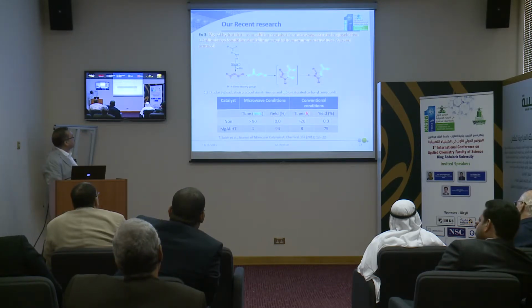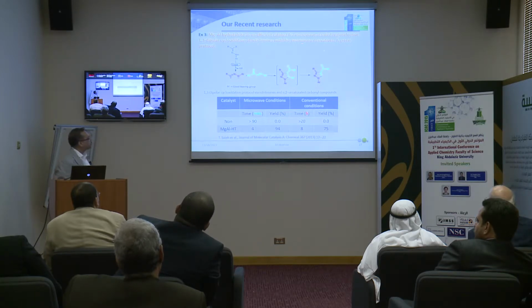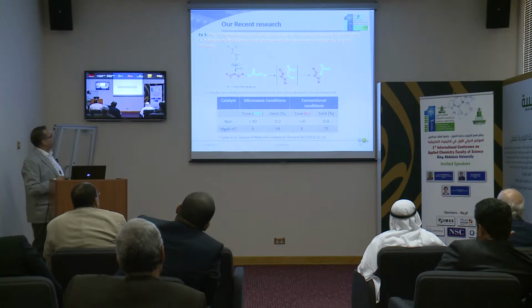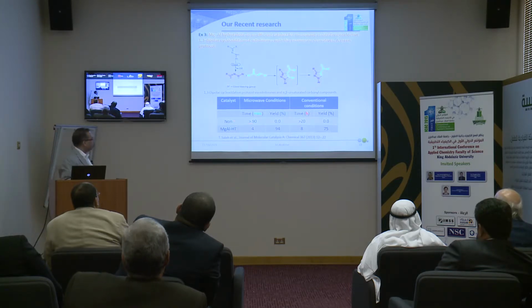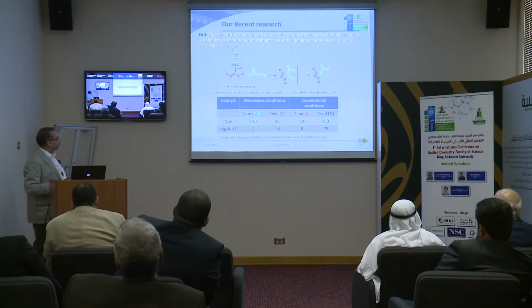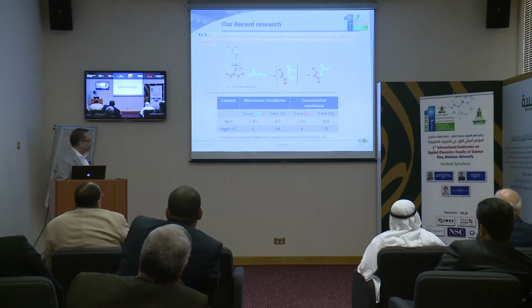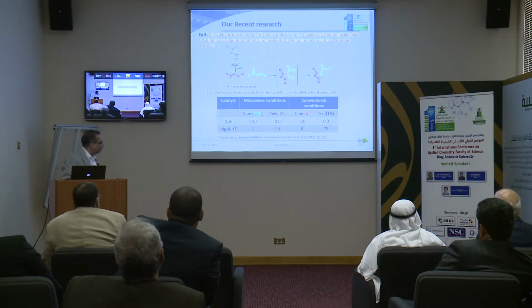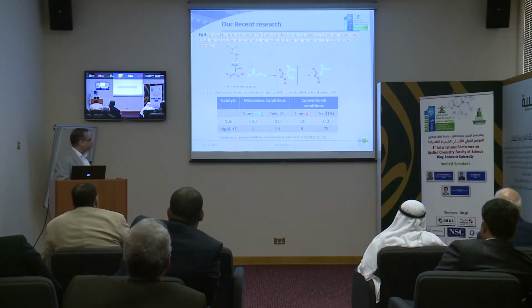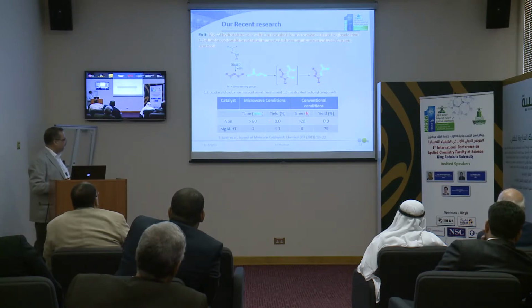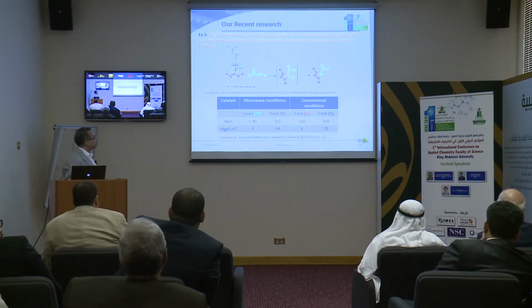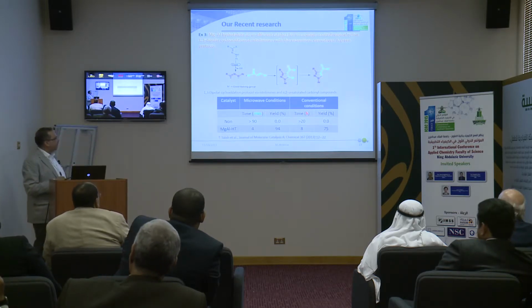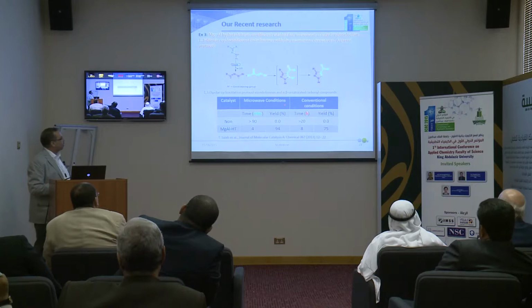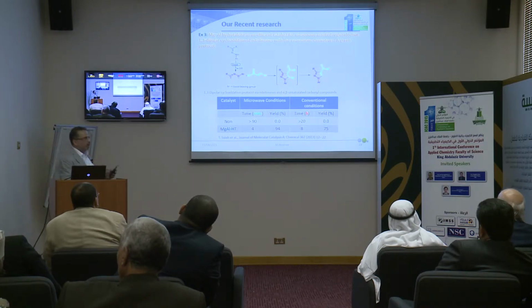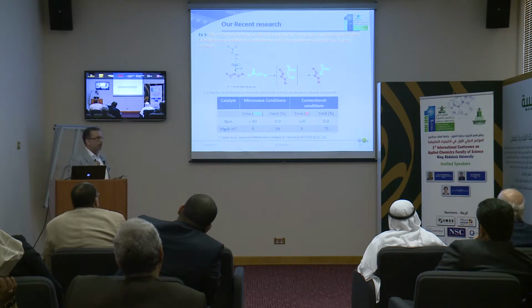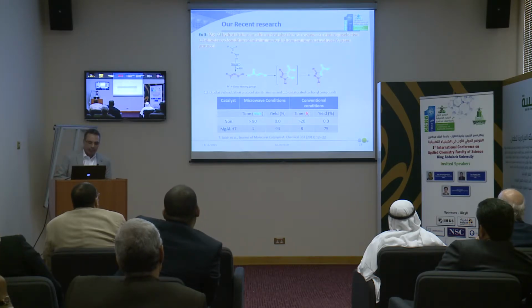Another piece of work used magnesium hydroxide itself as an efficient catalyst for the microwave-assisted regioselective 1,3-dipolar cycloaddition reaction. If we compare the catalyst using microwave conditions and the conventional one, we can find the yield shifted from 75% in the conventional method, while the microwave increases the yield and of course reduces the time. So now we mix in another tool for the green side of organic materials, instead of the hazardous classical methods of organic chemists using long times, hazardous materials, and lower yields.